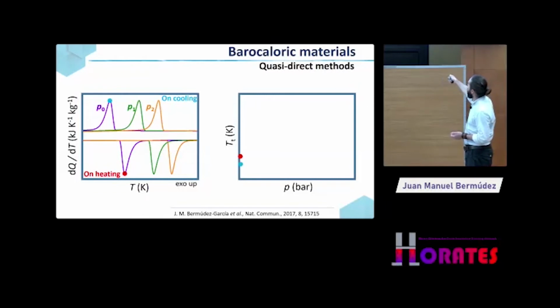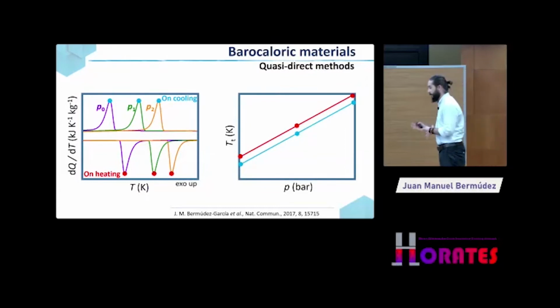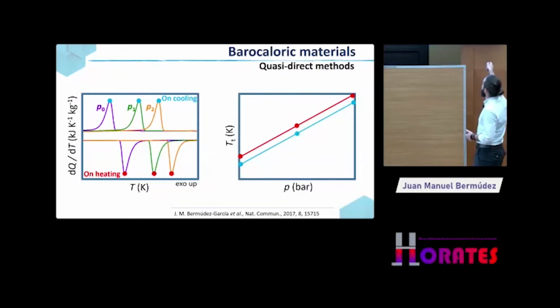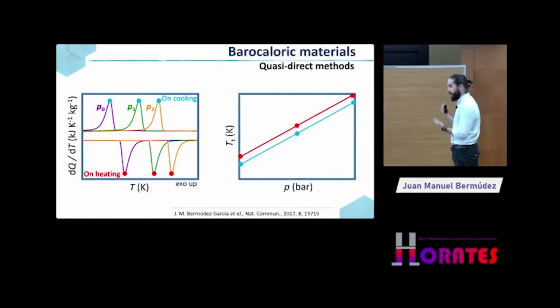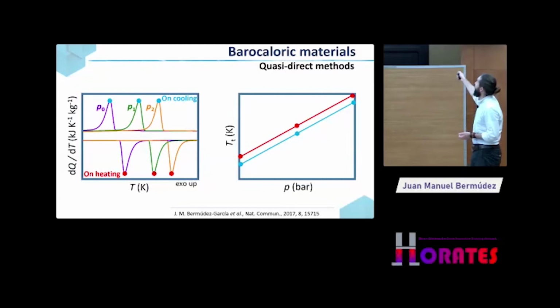So from here, you have all those points, and you have two parameters that we have mentioned before. First, you have the transition temperature dependence with the pressure, which was the barocaloric coefficient or the pressure responsiveness of your material. So the larger is this slope, the more sensitive is your material towards the pressure. And then you have the thermal hysteresis, which is gonna be the difference between the transition temperature on heating and on cooling, okay?